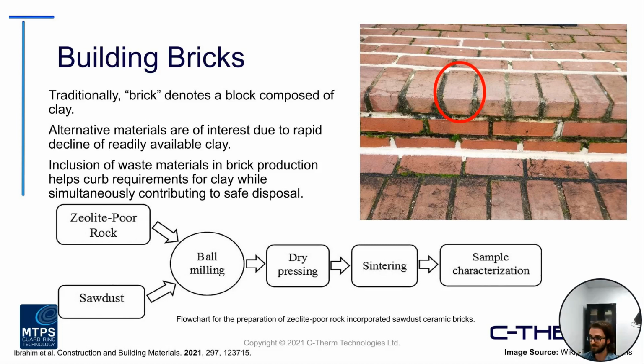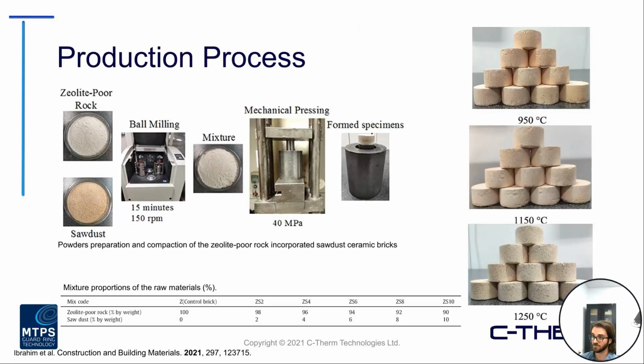So in this study, you can kind of see the flow chart. They are basically mixing this zeolite material and sawdust, going through this process, and then characterizing the end samples that were developed. So the production process, again, involved taking those powders or those materials and ball milling them, creating this mixture, and then pressing them into these cylindrical brick-like samples. And you can see here that they went through varying compositions. So your control, which was all zeolite, and then sawdust slowly, gradually increasing the amount of sawdust present inside the overall sample itself.